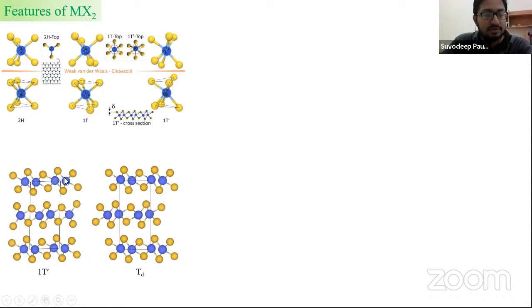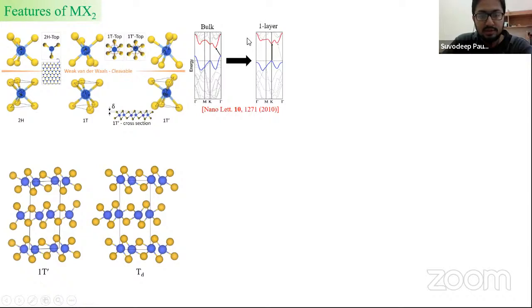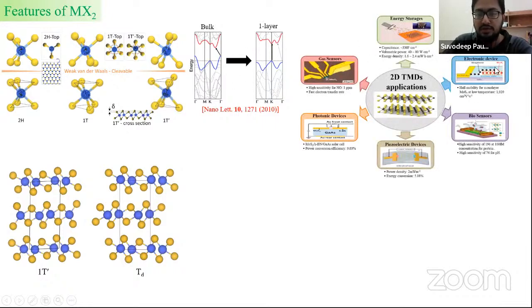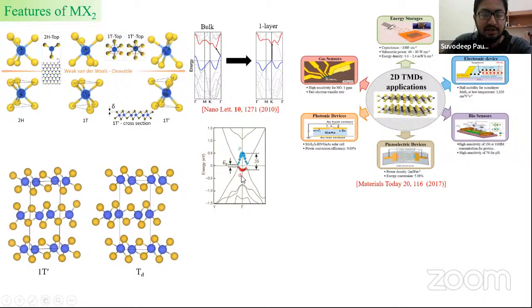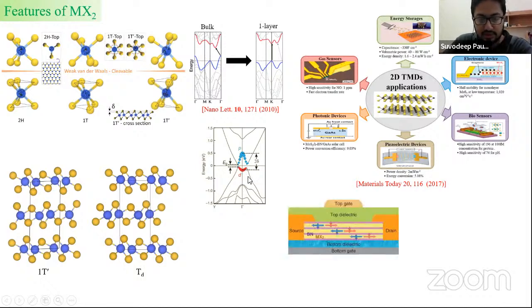Now, interestingly, all of these different phases also exhibit different properties. For example, the 2H phase exhibits a semiconducting band structure, which is also very thickness dependent. And as a result of this semiconducting nature, it has a plethora of different applications, ranging from sensors to electronics and optoelectronics, which are enlisted here in this review article. Then we have the 1T prime phase, which again has a band inversion in the band structure, and it's also characterized by a very small band gap opening.